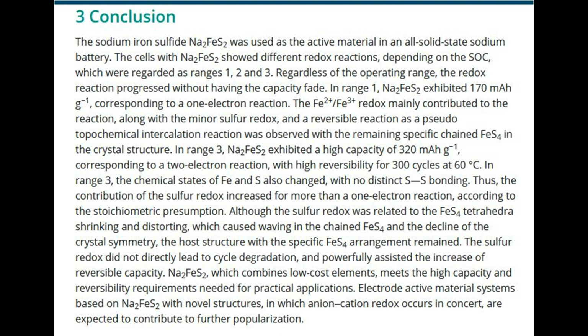Although the sulfur redox was related to the FeS4 tetrahedra shrinking and distorting, which caused waving in the chained FeS4 and the decline of the crystal symmetry, the host structure with the specific FeS4 arrangement remained. The sulfur redox did not directly lead to cycle degradation, and powerfully assisted the increase of reversible capacity.